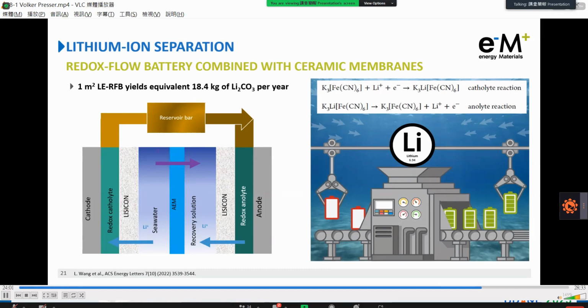In our system, we did some calculations and saw that for a 1 square meter lithium extraction redox flow battery setup, we would have an equivalent of around 18 kilograms of lithium carbonate per year recovered lithium from seawater. These numbers, of course, will greatly vary depending on the setup and system that you use. And in our system, specifically for the small scale, we used rather thick Lisicon membranes that slowed down the process significantly. More advanced membranes will yield a much more preferable uptake capacity and rate.